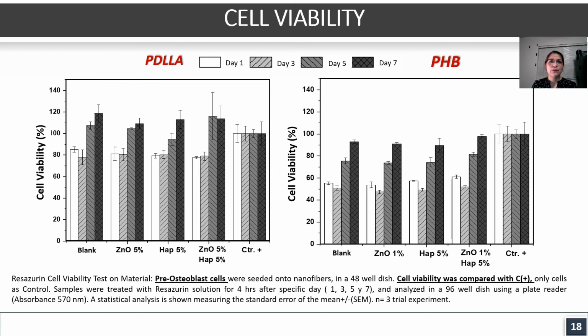In addition, it was observed that from day 5, there is an increase in the cell viability of both systems. This behavior could be related to the adaptation period of cells to the fiber environment during the first 3 days of interaction. Once the cells have adapted to the environment, they begin to carry out their specific functions, such as growth, proliferation, and migration, which result in an increase in the cell metabolic activity. In addition, the viability above 100% suggests that the positive control cells were close to their confluence, therefore no significant changes in their metabolic activities for days 5 and 7. In contrast, the scaffolds, by offering large surface areas and adequate porosity, allowed the cells to continue proliferating.